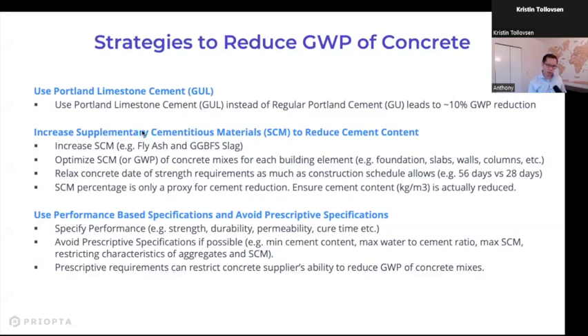Now, after you've done that, you can look at how to reduce the amount of cement content in your concrete mix. For example, using supplementary cementitious materials, SCMs. When you hear about things like fly ash or slag, these are SCMs, which can be used to reduce the amount of cement content in your concrete. And what you want to do is optimize the SCMs for each concrete mix, or sorry, for each building element in your building.